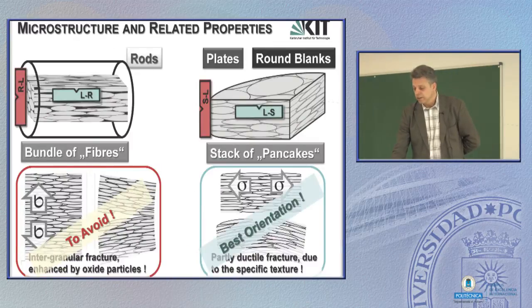Why is that? Let's compare the microstructure. Rods, as seen, can be considered as a bundle of fibers. It's like a fibrous material, whereas plates are more or less a stack of pancakes, if you want. And now, what we have said is that tungsten has very weak grain boundaries, so if you load a bundle of fibers, in this case, with tensile stress, then the grain boundaries experience full load. And since the grain boundaries are weak, they easily fracture.